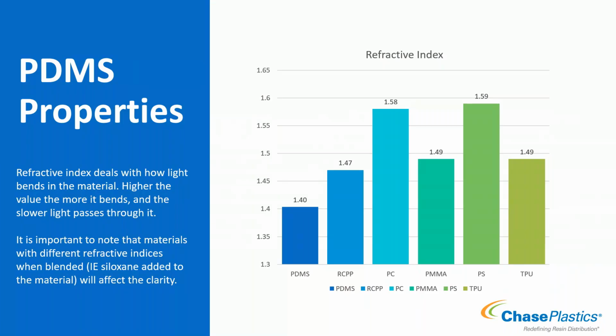So if you've ever run a polycarbonate and then you purged it out with a polystyrene, or you used a polycarbonate and added an additive to it and found that it starts to make the material cloudy, those two different materials that are combining have different refractive indices. And so you're going to end up with a cloudy material now instead of a material that maintains clarity. So it's not as easy as just, oh, if it's clear and I have another material that's clear, it's going to stay clear. It's not really how it works.